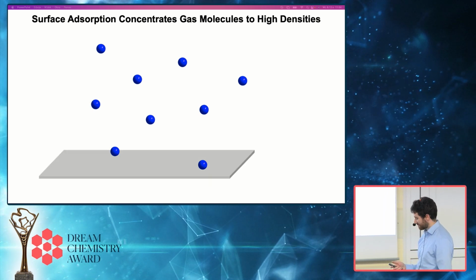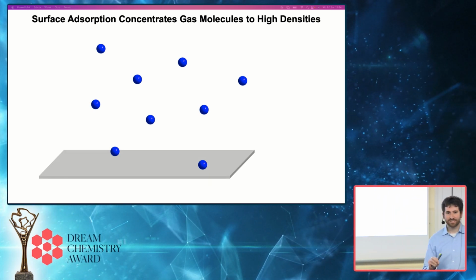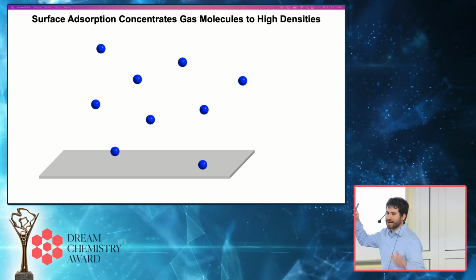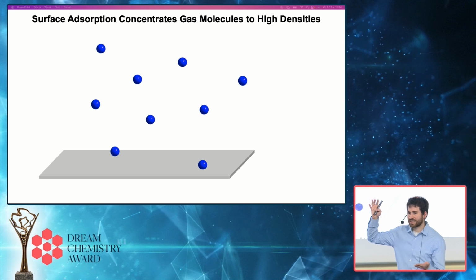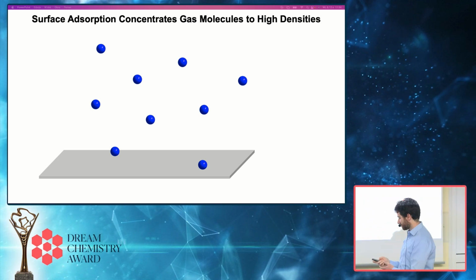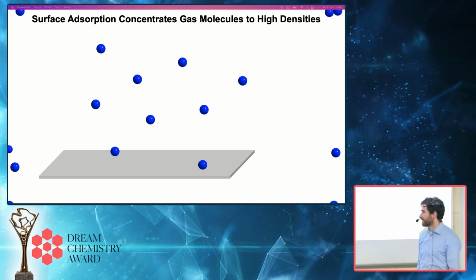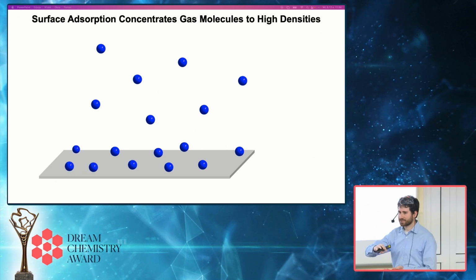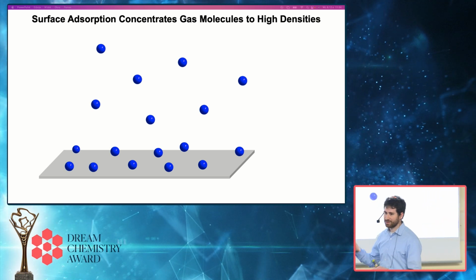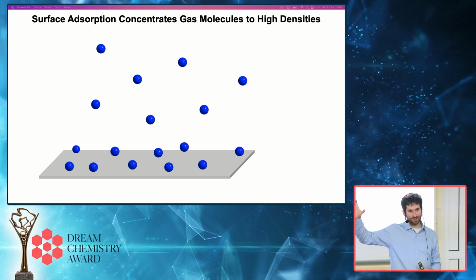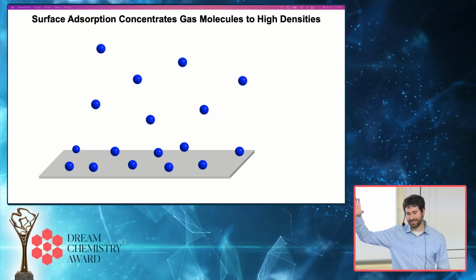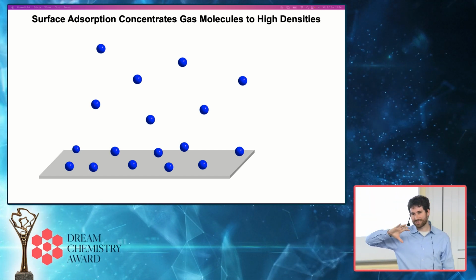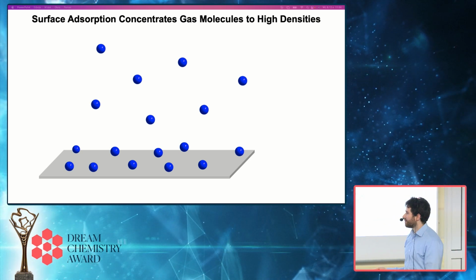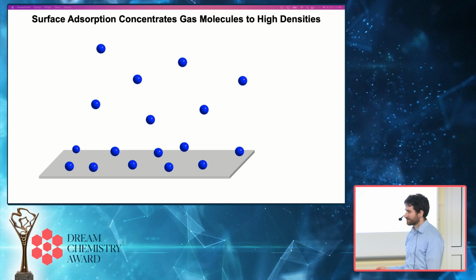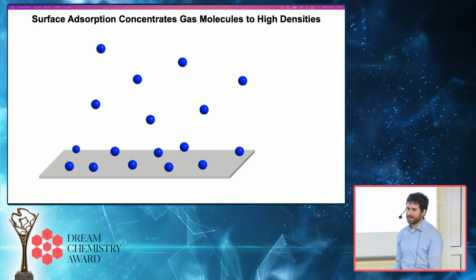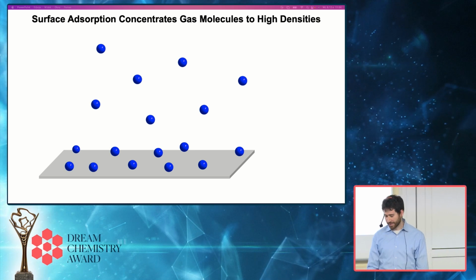You have a gas, imagine, say, oxygen, represented by these spheres that exist at some density in the gas phase. You put the gas in contact with really any surface. If there's any kind of attractive interaction, even weak ones, between that surface and these gas molecules, then you're going to increase the density of gas molecules present on that surface because of these attractive interactions. These can be very weak. You don't have to change the gas molecule itself, so there doesn't have to be electron transfer or chemical binding of the gas at the surface. Just very weak 5 to 10, even 15 kilojoules per mole van der Waals interactions that slightly polarize the electron clouds around gas molecules can have a big effect in increasing the density of a gas present at a surface.